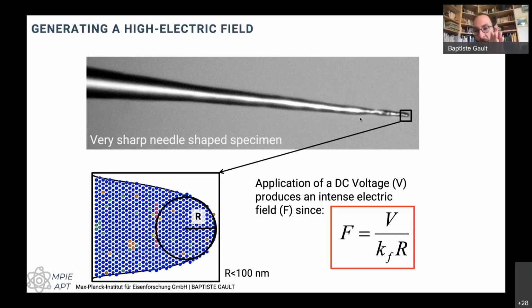I think overall, the time from a bulk sample to a needle is probably not that different through the two routes. But the advantage for me of the FIB is that you can prepare specimens specifically from a grain boundary, or from a grain that has a specific orientation, or from materials that are non-conductive. I think that's really the key difference.